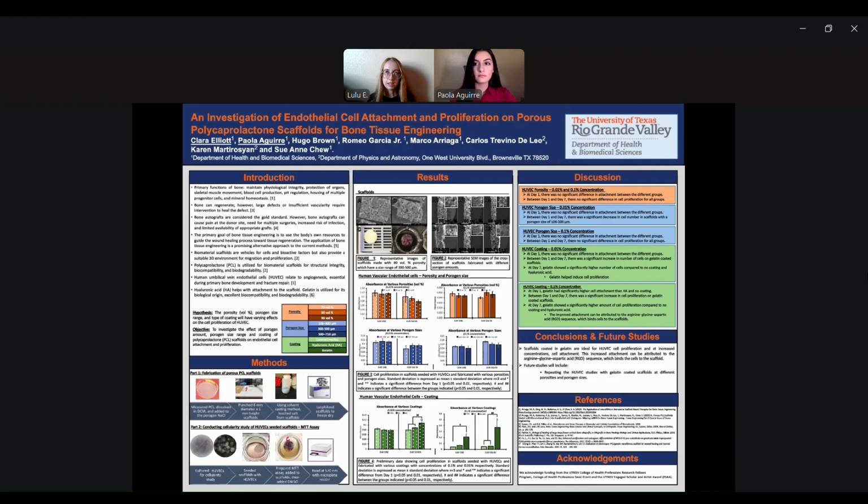But it comes at the cost of these scaffolds being a bit more delicate, and they also degrade at a quicker pace. In contrast, our lower surface area scaffolds like these 70s are definitely a bit tougher, but they're less flexible, and there's less places for the cells to adhere to. So depending on the injection site, these details can really matter, especially when it comes to the rate of degradation, depending on the injury that's being treated.